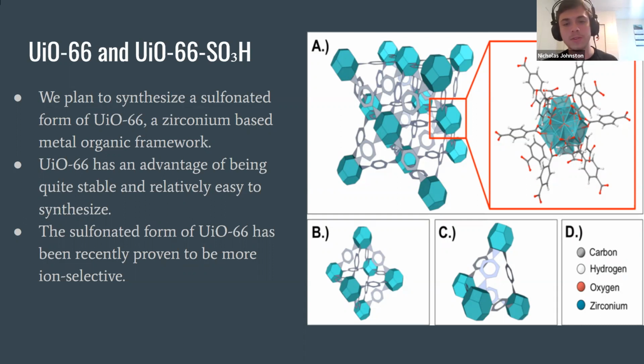Dimethylformamide. You probably have seen it abbreviated as DMF. Actually, maybe not, but you will. And you would put that in a vessel for 24 hours at 120 degrees Celsius or so. The figures I'm reading off are from a scientific paper, I think the very first one that synthesized UiO-66.